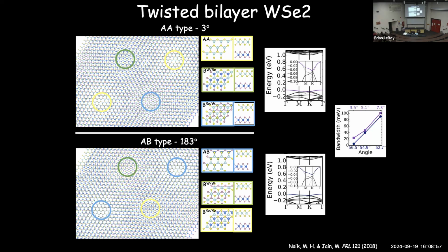And because of that, if you look at what happens to the band structure in these materials, you end up getting slight differences between them. But in both cases, as you make the twist angle small, you get large domains here. And the valence band that had this curvature to it flattens out. You end up getting a very flat valence band in both cases. And the bandwidth, how much curvature there is in that band, drops with twist angle. In both cases, going towards 0, becoming a flat band as you approach either 0 degrees or 60 degrees.